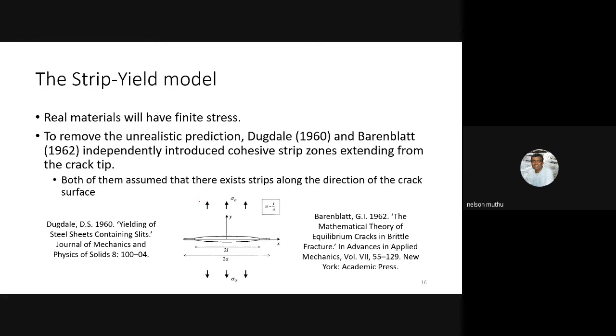Whereas in the strip yield model, that we are going to see now, Dugdale and Barenblatt viewed things from a slightly different perspective. In fact, both of them independently introduced cohesive strip zones. These are called cohesive strip zones extending from the crack tip. You can see the literature in the references I mentioned on either end of the slide. What they assumed was that there is an initial crack of length 2L, but all the plasticity is confined to this zone. They call these strips. Therefore, the actual crack length is 2a.